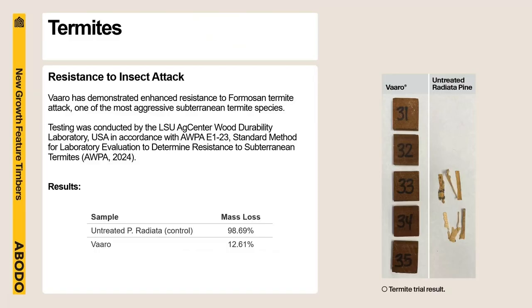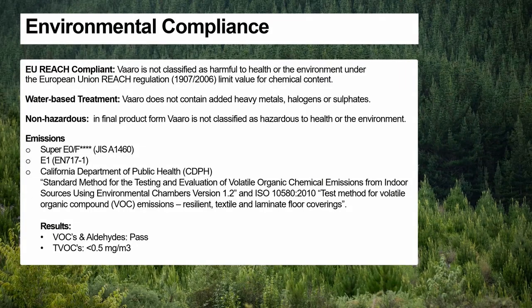We conducted termite testing against the Formosan termite and found that the Vaaro had excellent resistance to this termite. This is one of the most aggressive termites in the world. As you can see on the right, untreated radiata pine fully destroyed and the Vaaro remaining intact. In terms of environmental compliance, Vaaro is not classified as harmful to health or the environment under the European REACH regulation. And because it's also a water-based treatment and does not contain any heavy metals, halogens or sulfates, which are typically often contained in traditional fire retardant treatments. And in its final form, the product is non-hazardous.